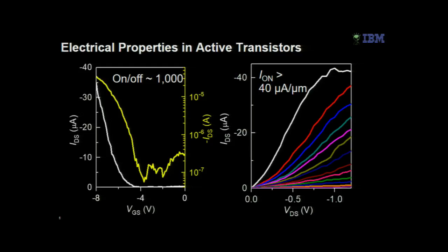simulation. Transistors built on such semiconducting nanotube arrays demonstrate good performance, with off ratio approaching 1,000 and on-state current density above 40 microamperes per micron, which is decent. But still, it is about an order of magnitude or more less than current silicon transistors due to the nanotube density being limited to only 50 nanotubes per micron. So a better approach is probably to let the statue build itself, which means to form